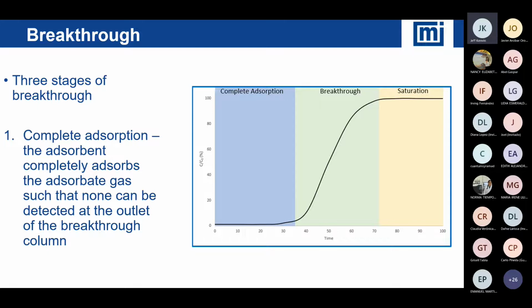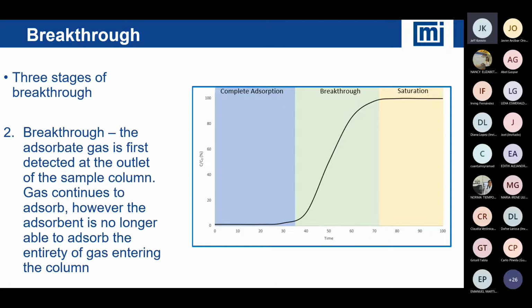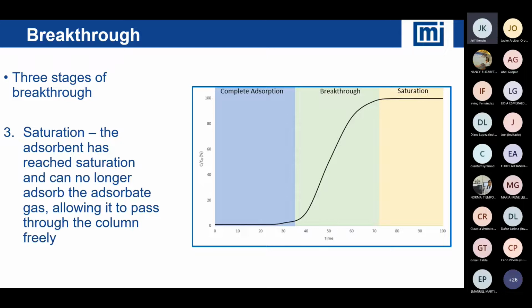Okay. So as we look at breakthrough, there are really three interesting pieces of the breakthrough experiment. We're simply flowing gas, and we can flow a mixture, and then we're going to monitor what basically elutes off of the sample. So at the inlet, I could have water and CO2, and then I want to know, when does the water come through? When does the CO2 start to break through? So how much of each is going to be adsorbed? Is one preferentially adsorbed versus the other? If we don't have any signal, that's typically complete adsorption, versus if we start getting to a region where concentration is increasing, in the green in the center, that's typically breakthrough. And then when we get to the final stage, all the way on the right side, the material is completely saturated, so it has a stable concentration on the surface.